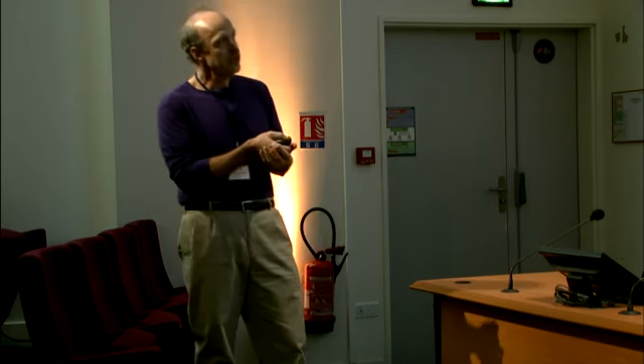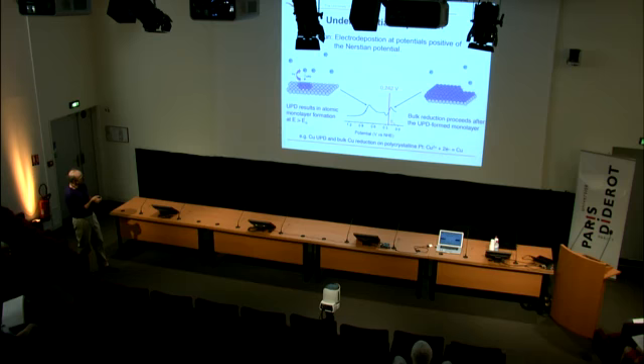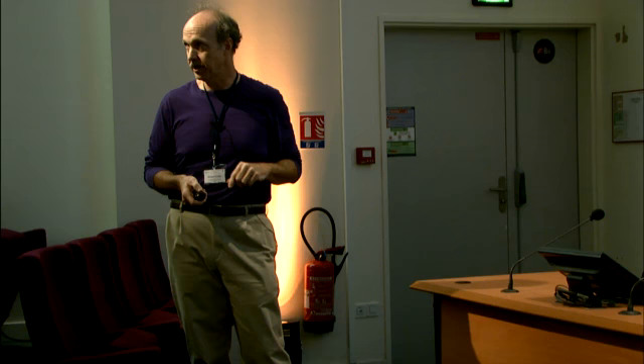And so just a single monolayer of copper will deposit on this platinum surface, and then after there's a monolayer, now I'll start to see bulk deposition of copper, and I'll see multi-layers grow real quickly. Okay? So for what we're going to do, we're always going to be to the left of this line. We'll always be doing underpotential deposition.